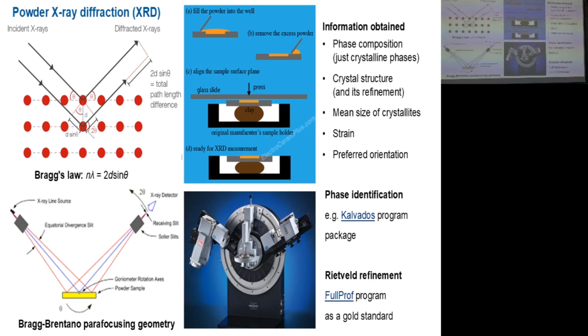So if you have your powder sample from the lab, and if you want to do powder X-ray diffraction, most probably some powder diffractometer with the Bragg-Brentano parafocusing geometry will be available to you. It's schematically shown here, and the important point in this geometry is the localization of the X-ray tube and the detector, that both of them have the same angle with respect to the plane of the sample. So here is the X-ray source, the X-ray tube, here is the detector, and here is your sample. In this case, the sample is introduced to some dish like this.